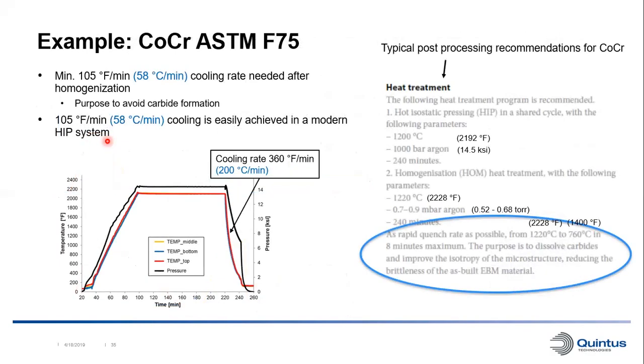And here we can see an example of high pressure heat treatment. This is for a cobalt chrome material, and this specification I've taken from a material supplier website, which is actually Arcam's website, so it's a 3D printing company website, but it makes a good example. And here are the recommended post-treatments of their cobalt chrome parts. So first, they recommend a HIP cycle at 1200 Celsius at 100 megapascals for 4 hours.